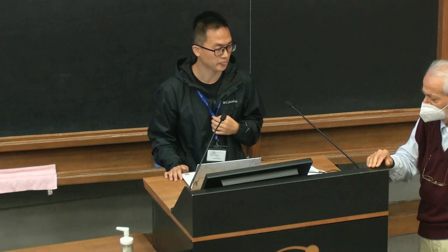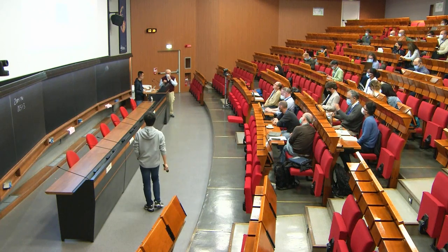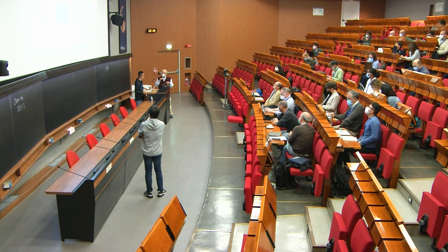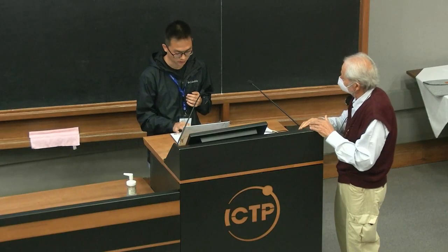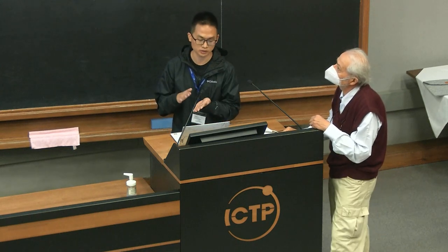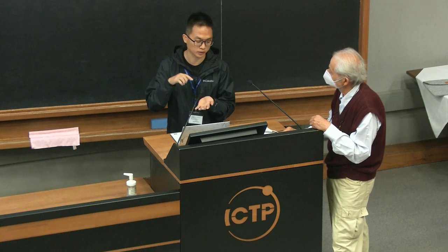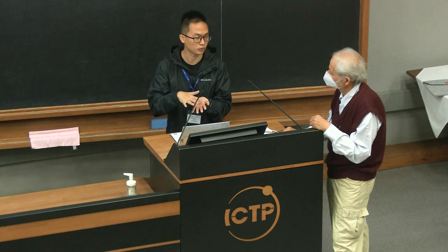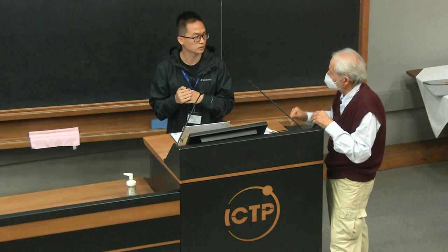A question myself. You said in the beginning that the friction will go down with the number of buckling events. How does that happen? This can be understood from the energy profile. For some dislocations, if the transition energy barrier is very high, during sliding it will stay in this state and cannot buckle. As we increase the normal load, this reduces the barrier, and it can buckle during sliding. If you have a very large slider, I see. Yes. Okay.